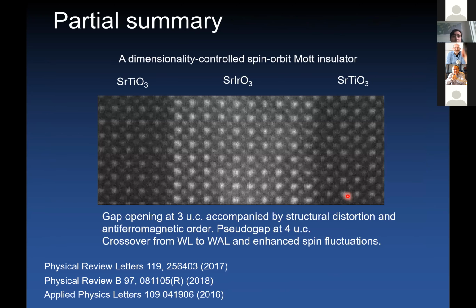Okay, so this brings me to my first partial summary of this first project. I showed you that with the interfaces of strontium iridate, you can change the dimensionality of strontium iridate going towards the two-dimensional limit, and engineer a correlated insulating state. So this occurs, the gap opening at 3 unit cells of strontium iridate, with a pseudogap behavior observed at 4 unit cells. And in this regime, the system crosses over from being weakly localized to having weak anti-localization with a strong enhancement of spin fluctuations.